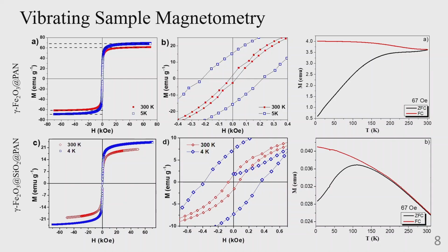A value of magnetization of 60.3 emu/g and 68 emu/g are obtained for 300 K and 5 K respectively. By zooming the field in the interval plus minus 0.4 kilo-oersted, some features of the magnetic behavior of the sample can be observed better.